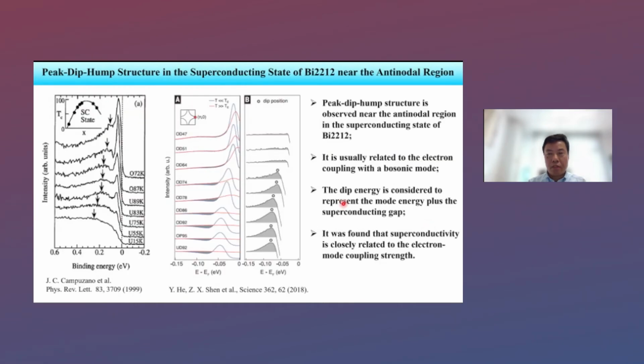Also, in the high Tc superconductors, there is a famous so-called peak-dip-hump structure in the superconducting state. You have a peak, you have a dip and a hump structure. This is considered a hallmark of superconductivity in Bi2212. So it has been used as a fingerprint of superconductivity.